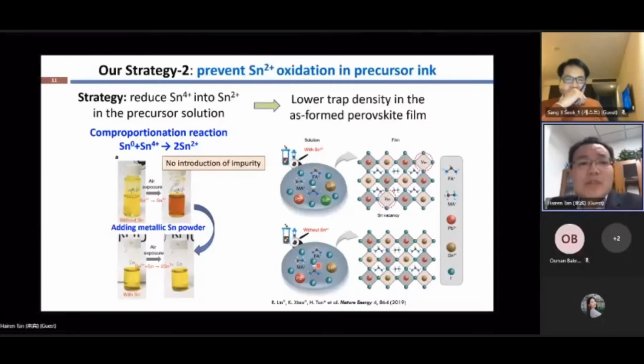But with the previous 2D layer capping on the surface, we still found quite a high ratio of tin oxides in the perovskite materials. So we thought maybe this oxidation already happens in the precursor solution. If this happens, it will be incorporated in the perovskite film, and it will generate p-type doping and also tin vacancies in the materials. So if we can prevent the tin oxidation in the precursor ink, we have a way to much reduce the tin vacancies and also reduce the p-type self-doping.